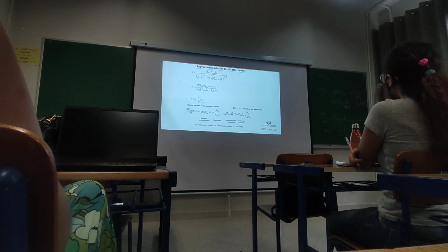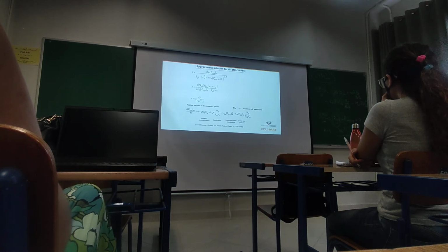And in the aqueous phase, the concentration of radicals is huge again. Okay, even if the concentration is very low, the number obtained by multiplying by Avogadro's number is large. So this is again the problem from before, the problem of compartmentalization. The radicals in the particles are distributed among lots of particles, and therefore in each particle there are very few. Okay, so as I said, this is also a transient species. We can apply pseudo-steady state, and we have an algebraic equation.